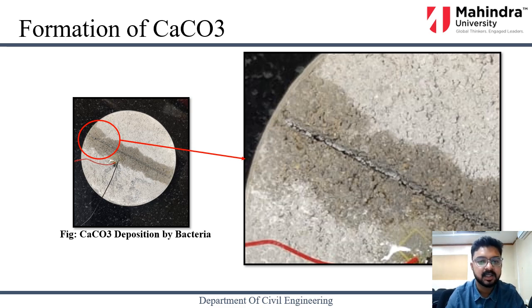And here in this picture you can see this is a 0.5 mm crack. We have acquired the data for 15 days, and you can see there are some white deposits inside the crack. This is because of CaCO3. Generally in concrete, calcium is present because of cement, and CO2 from the outside and OH ions will combinedly form HCO3, and at more than pH 9, HCO3 will divide into CO3 2 minus and H plus ions. As we know, concrete is more alkaline in nature, and its pH is around 12 to 14. H plus ions will be removed from the HCO3, and this remaining CO3 2 minus then reacts with the calcium which is present inside the concrete and forms CaCO3.